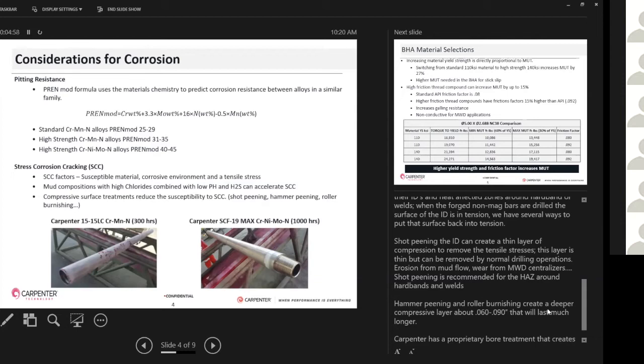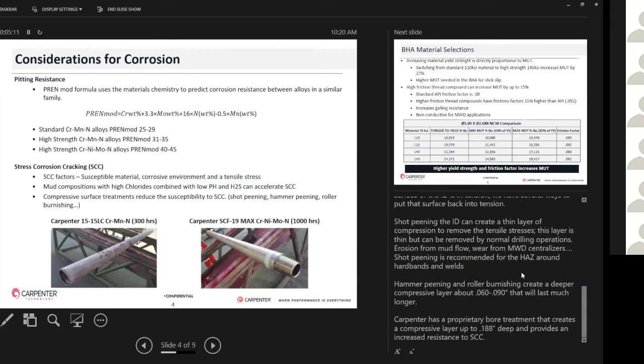Shot peening is recommended for the heat affected zone around hard bands and welds just because of the adaptability to shoot at different angles and create that compressive layer in different areas. The other option for you is hammer peening or roller burnishing. That creates a little bit deeper compressive layer, about 60 to 90 thou. That lasts much longer than the shot peening on the IDs of collars. At Carpenter, we have a proprietary bore treatment that creates a compressive layer up to 188 thou deep, and it provides an increased resistance to stress corrosion cracking versus the other two methods.